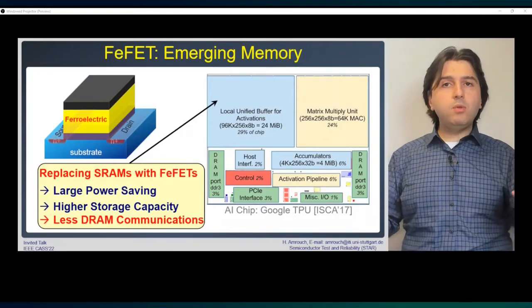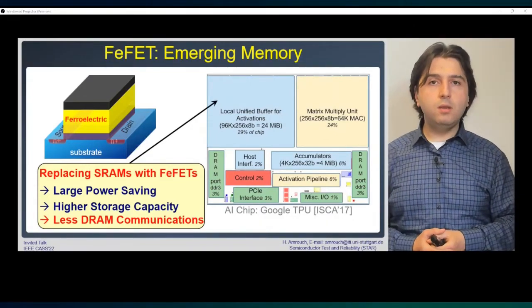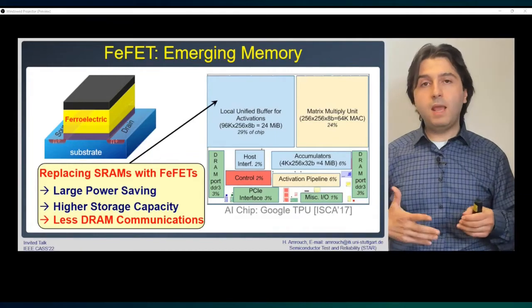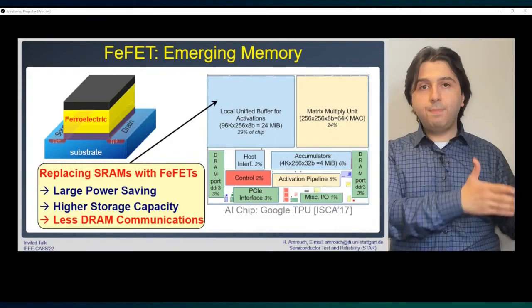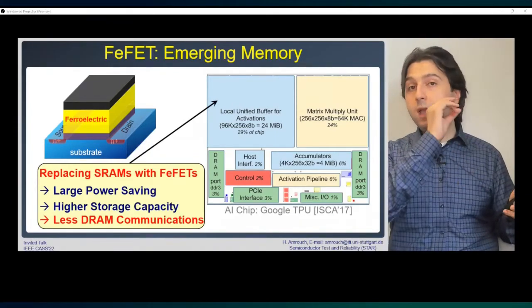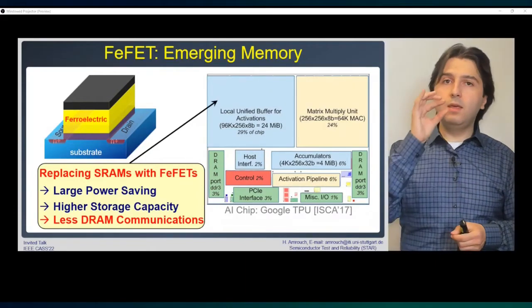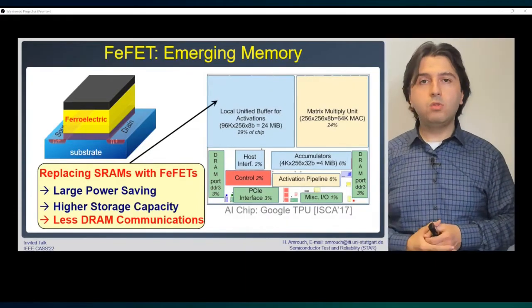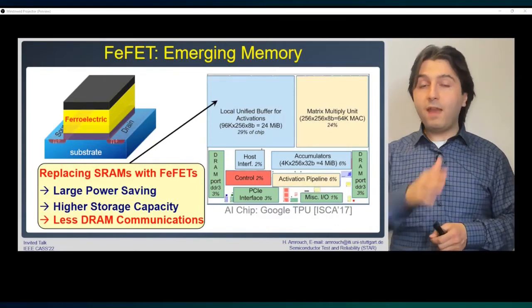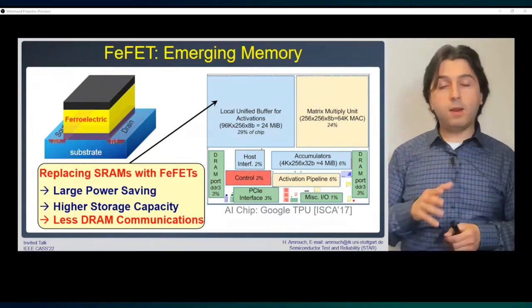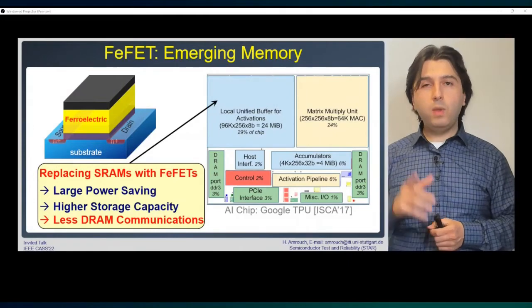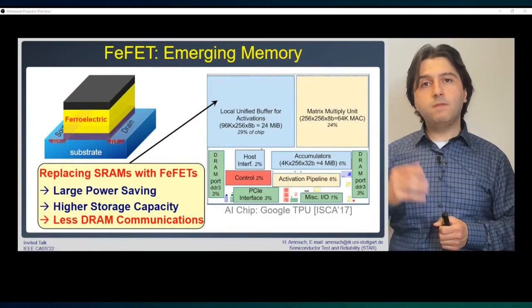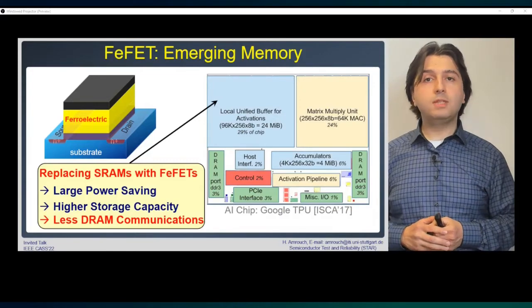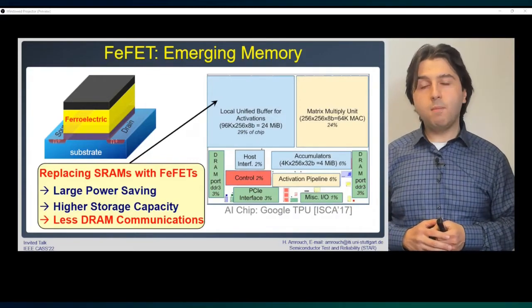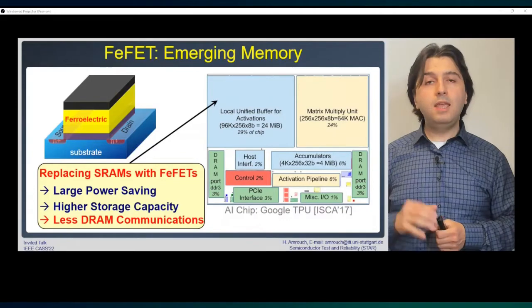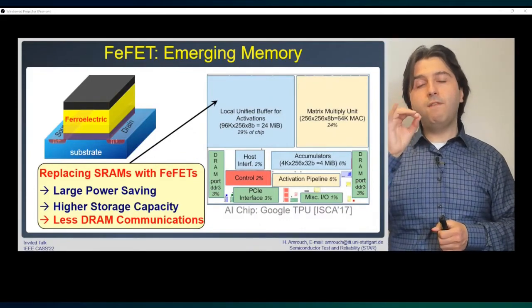Now, the beauty of this ferroelectric technology, as you see, is that in theory you would be able to realize a steep slope transistor with NCFET when the thickness of the ferroelectric is very thin, let's say around 2 to 3 nanometers. In fact, there was even a breakthrough, a real breakthrough, just very recently, 2 weeks ago, a paper from Sayeef Salahuddin from Berkeley published in Science, and they showed for the first time that ferroelectricity can be realized even at a thickness of 0.5 nanometers.